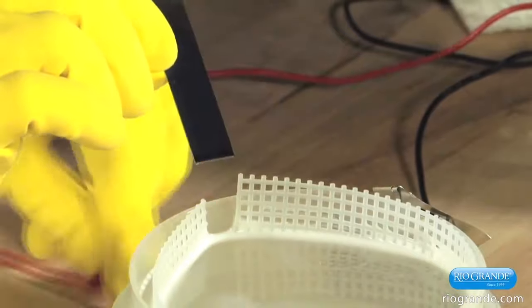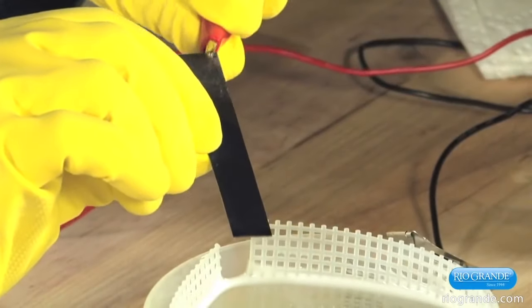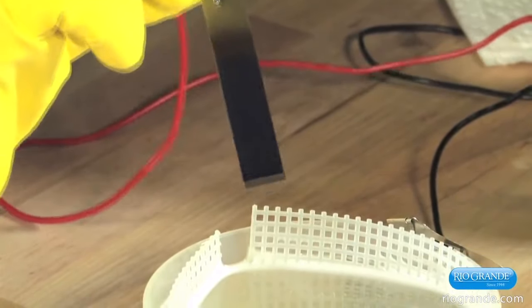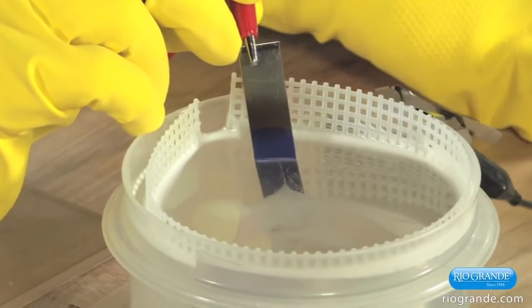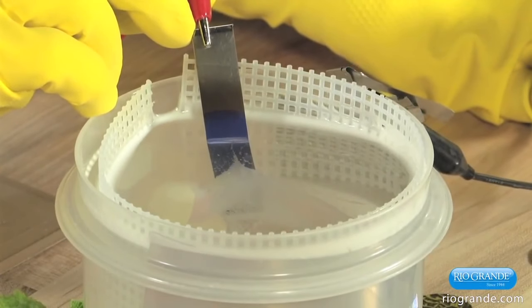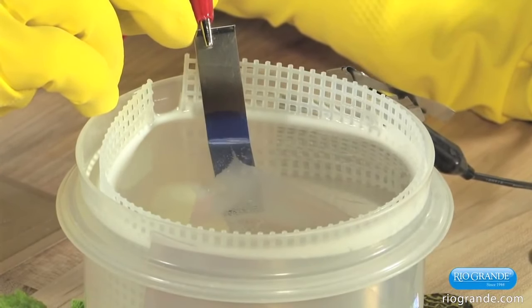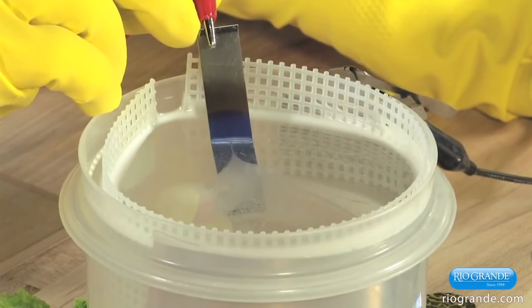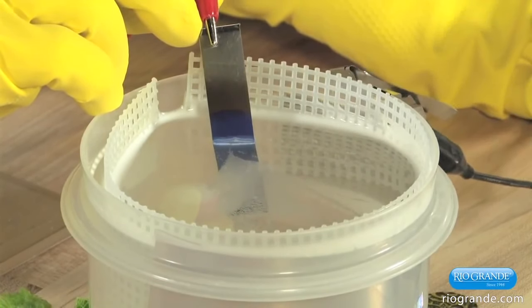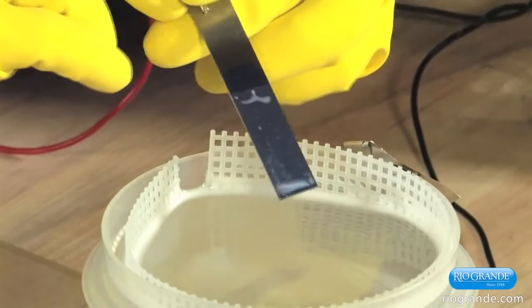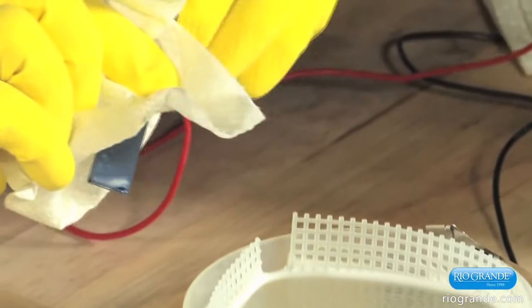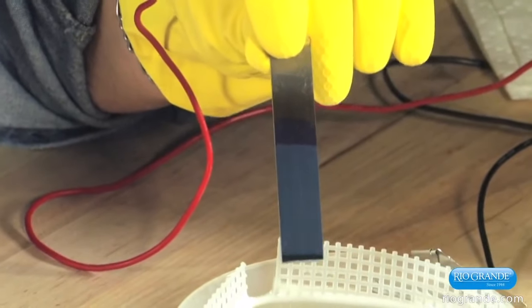And we'll do it one more time. Submerge it again part way, and I'll turn it up to about 30 volts. Now we have a light blue.